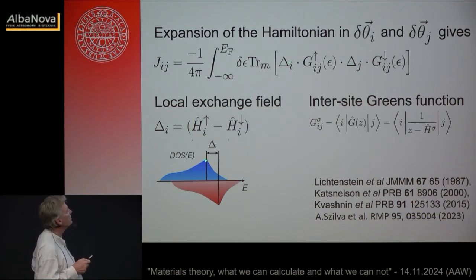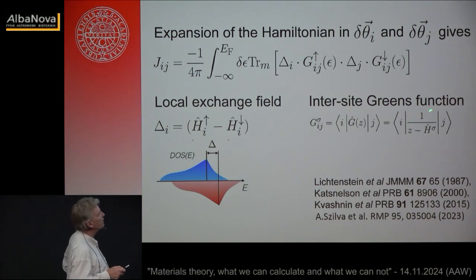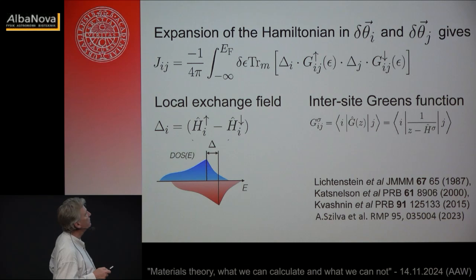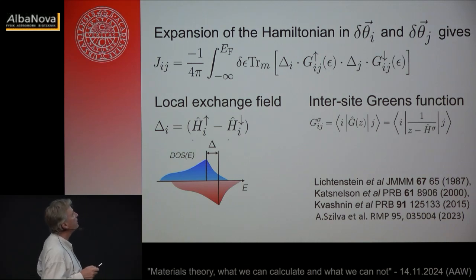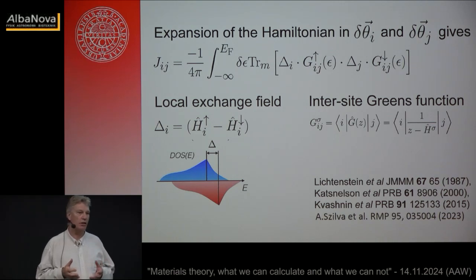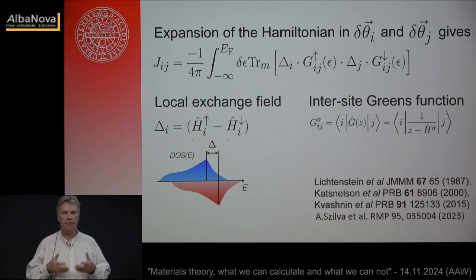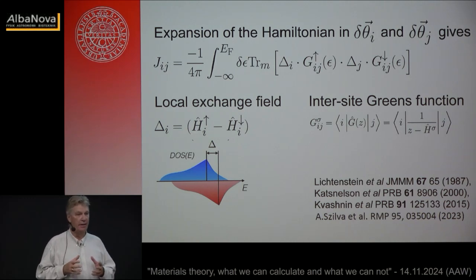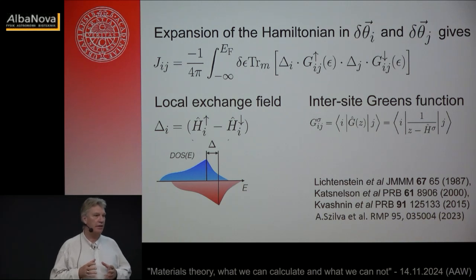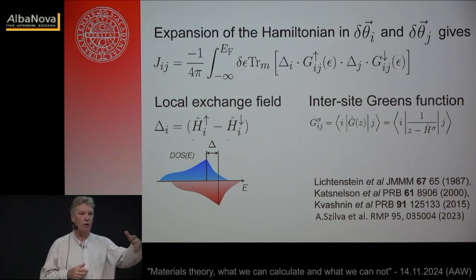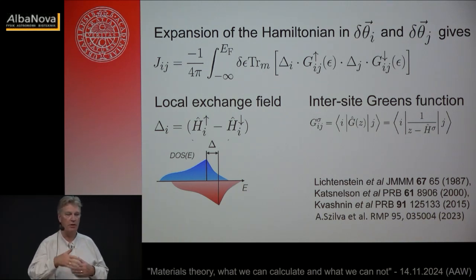So it's just exchange splitting, what we discussed for BCC iron, and then a Green's function, which is basically 1 over the Hamiltonian, z minus Hamiltonian. And the expression is this guy here. So this means that it's perfectly possible to do a calculation for something very simple, 1 atom per unit cell. And then it's very simple, very quick, very fast, no computational efficiency issues. And nevertheless get the information about exchange interactions in the material that go out as far as you want into the material. Nearest neighbor, next nearest neighbor.